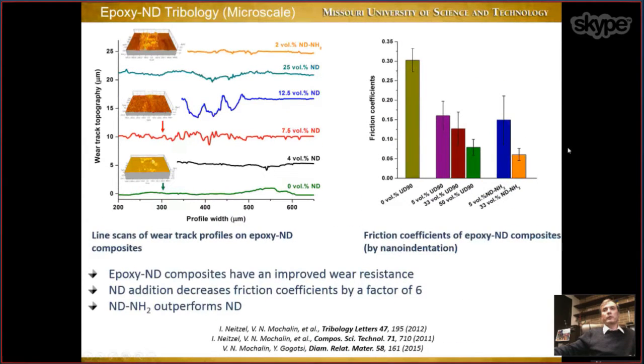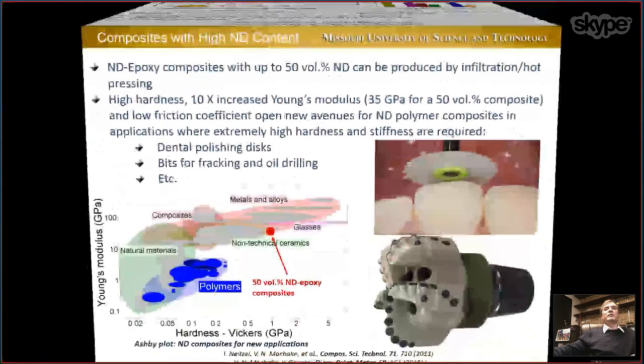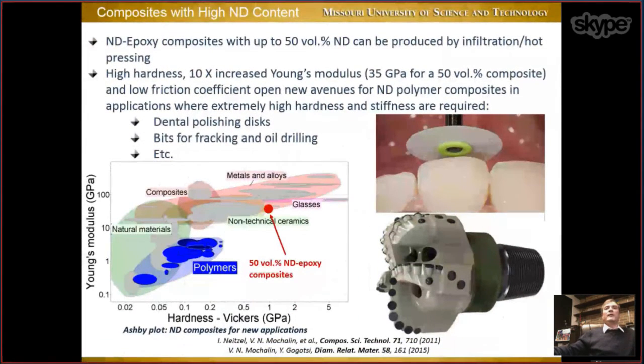So this is for 33 volume percent of aminated nanodiamond. The friction coefficient is the lowest compared to all other materials. This is neat epoxy, other different nanodiamonds in different amounts. So basically when you covalently incorporate high concentration of nanodiamond into epoxy, you achieve very low friction coefficient. So the applications for this material come to your mind immediately.